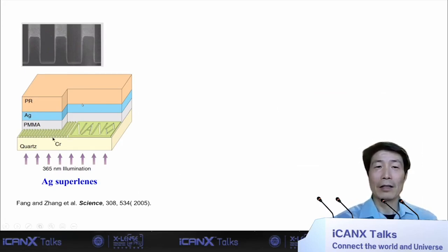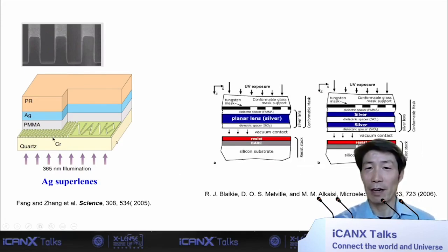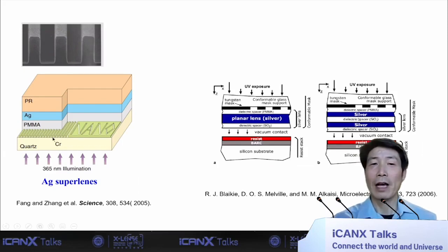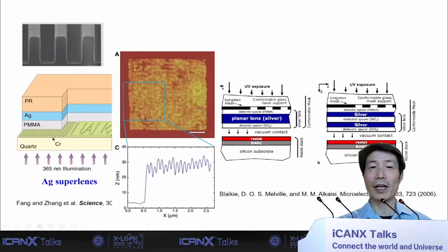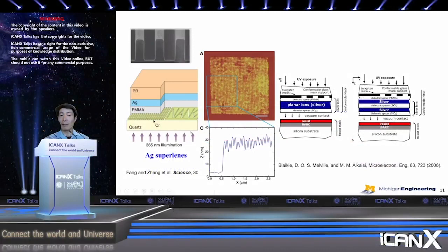Okay. Now, a year later, another group from Australia, the Blaikie group, also demonstrated something similar. See, planar silver, right, and the mask on top, or double silver layers, multiple layer film. Okay. So both of them were able to demonstrate, for instance, using ordinary UV light, you can resolve, I don't recall the exact dimension, but probably 70 nanometers, right? Much smaller than the wavelength. This is sort of getting beyond the diffraction limit, okay? And work done by the Blaikie group also similar.